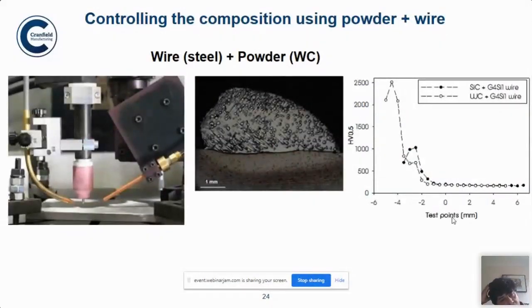This is another example of creating a composite part. So this is for a brake disc project that we did a few years back, and here you can see that the weld bead that is shown in the middle picture has tungsten carbide embedded in it. So how have we done this? It is shown on the left. It is a TIG arc, and then you feed the wire from this shaped wire feeder, and you blow powder inside it so as to make a composite structure.